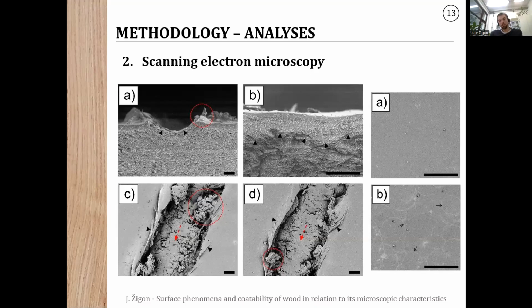Here we see some scratching, like I showed before with the confocal laser scanning microscopy. This time the same scratches were analyzed with the SEM. So what's happening with the coating in detail, on the cross section and on the surface. So we see some damages. And on the right side, we see 2 images. Above is before artificial weathering and below after artificial weathering. This shows how the damage on the coating film of wood is happening or is observed from the surface.